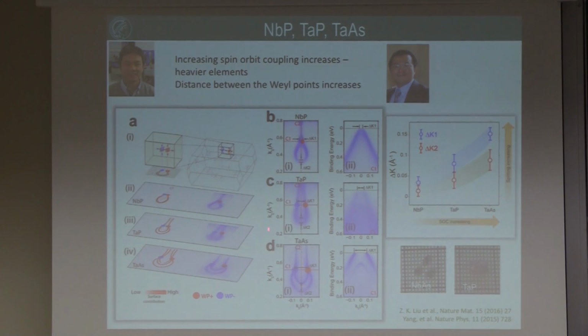The first thing we did is we looked for the Fermi arc, so we did calculations of potential Fermi arcs in the family niobium phosphide, tantalum phosphide, tantalum arsenide. We had all the crystals, and you see you make the material heavier and heavier, and it's very simple: spin-orbit coupling increases in the same way, and you see nicely how the calculation, DFT calculation, compares with the measured photoemission data done by Julian Chen's group.